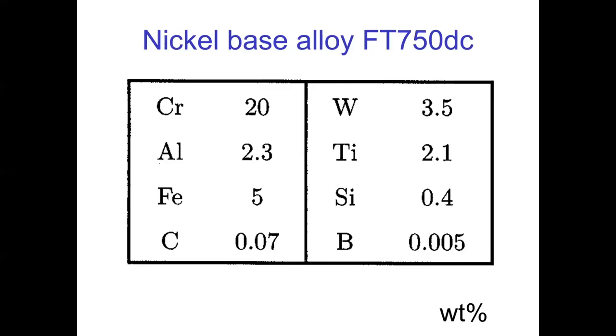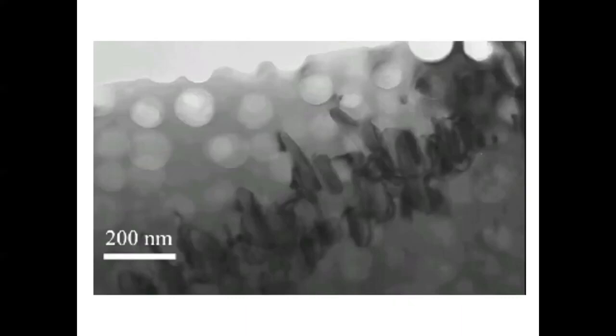But as I said to you, ultimately what we need is properties. So this is completely theoretically designed, right? And the property part was designed by taking the vast amount of public domain data that we have on nickel-based superalloys and doing machine learning. So this is the alloy microstructure where you have these gamma prime particles, but the volume fraction here is only about 20%, whereas in an aerospace alloy, it would be of the order of 70% in the blades. So it's a very simple alloy composition, and the structure is as we would like it.